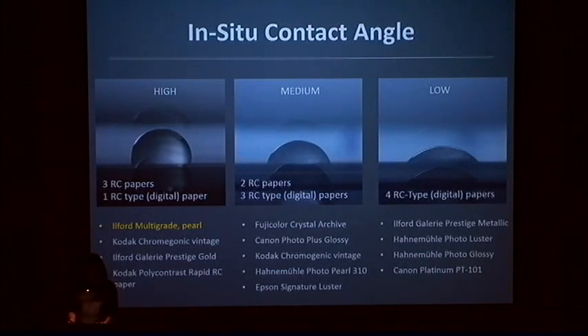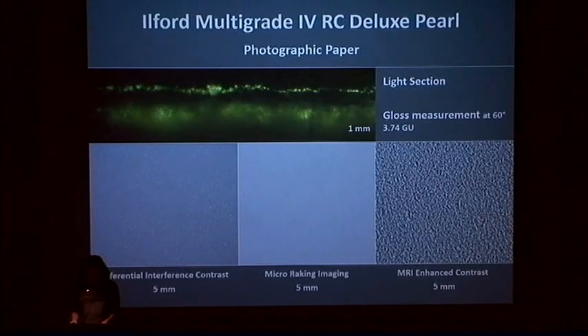The ILFORD Multigrade, which is in yellow, is the paper we are using in our original adhesive testing because this is a true polyolefin, meaning it is hydrophobic and relatively difficult to get adhesive to stay stuck. We are conducting surface characterization studies on all these paper samples to evaluate if and how surface roughness influences adhesion.